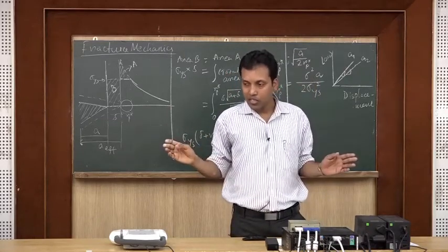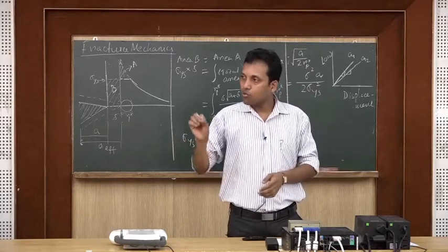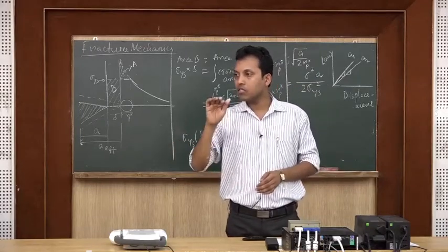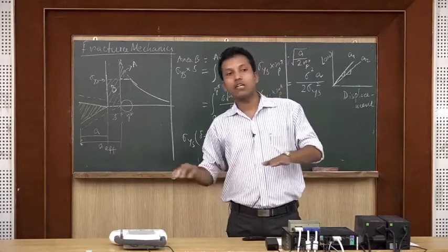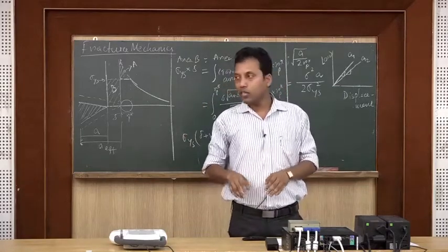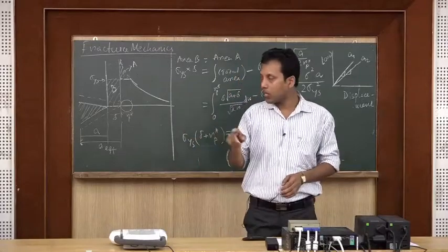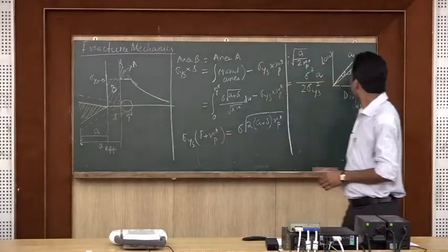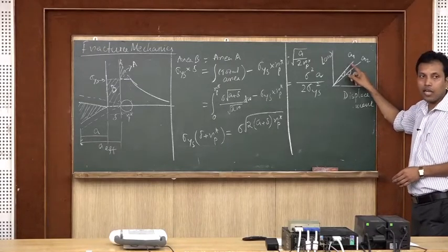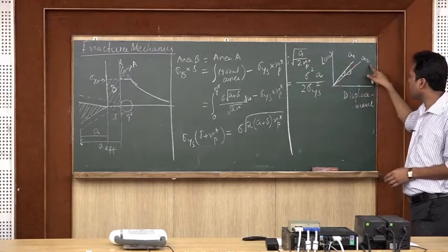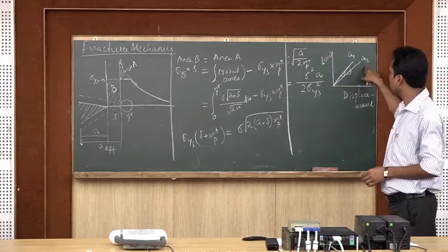Why then we are thinking that that is a crack is present? That is tricky thing. The trick is due to presence of a plastic zone, material stiffness reduces, and that stiffness reduction we try to correlate with crack length. If crack length of certain length is there, then this is the curve, load versus displacement curve. Now, if a crack length of say higher, here you can write A1 less than A2.